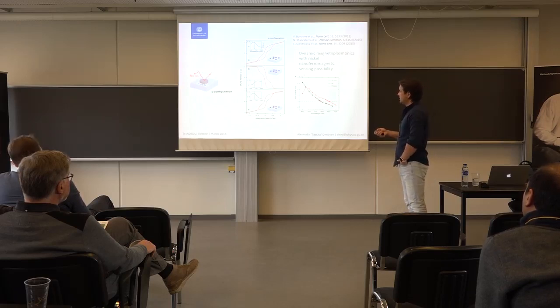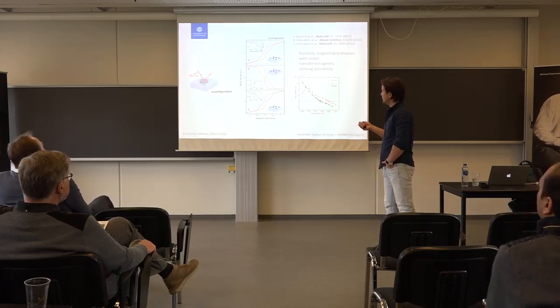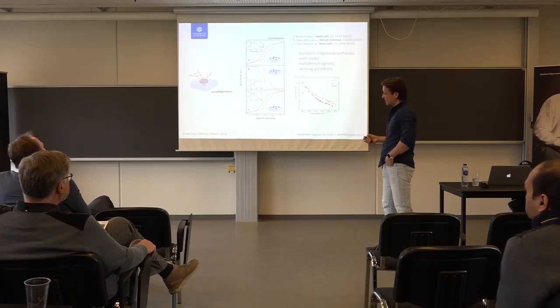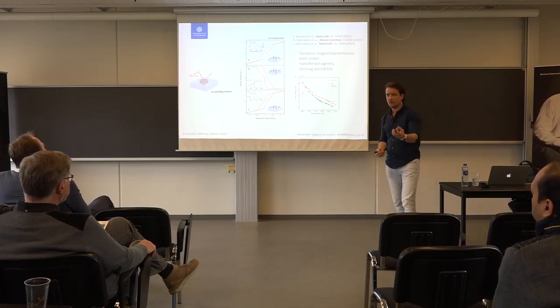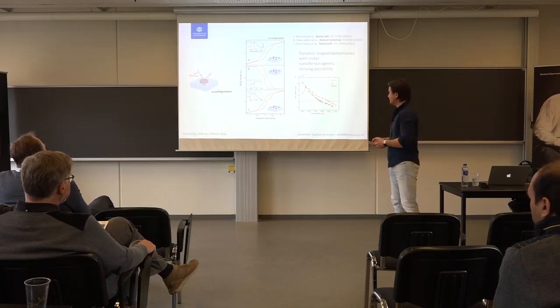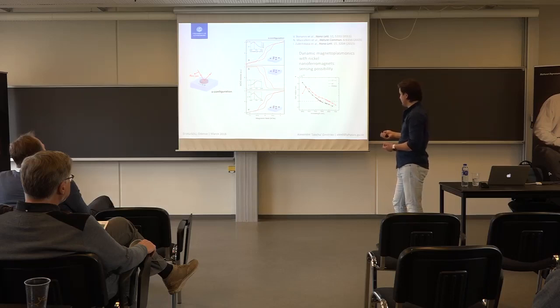It's interesting that when we mess up the system here, we add a little bit of refractive index difference to our plasmonic antennas. Plasmonics is known to be sensitive to the surrounding index. This is how plasmon sensors are working. You add the molecules, and then your resonance feels the presence of that molecule just by the fact that the refractive index is changed around that plasmon resonance. So here, exactly that's what we're doing. We're changing the refractive index, and the whole thing is actually moving to the red.